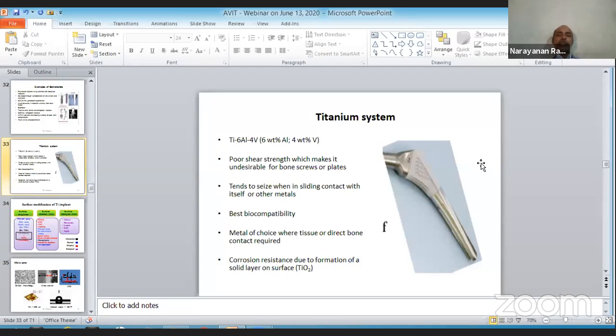Although titanium is technically better, there are three limitations: their fabricability, their poor friction, and their lack of availability. So that's where we go for the alloys. I mean, titanium as well. Pure titanium is used in dental applications, whereas the alloys, with aluminum, vanadium, or niobium, titanium, zirconium, are used in bone applications, knee applications or joint applications. But as a whole, whether it is pure titanium or titanium alloys, they have all these three inadequacies.